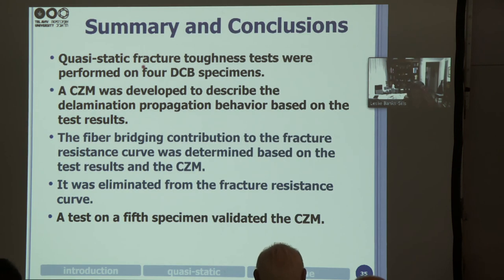And so we've reached the summary and conclusions. We carried out quasi-static tests on 4 DCB specimens. The cohesive zone model was developed to describe the delamination propagation behavior based on the test results. The fiber bridging contribution to the fracture resistance curve was determined based on the test results and the cohesive zone model, and it was eliminated from the fracture resistance curve. And a test on a 5th specimen validated the cohesive zone model.